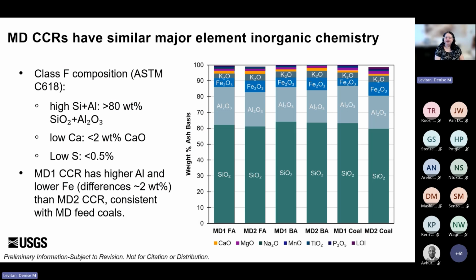So the CCR material from these two plants have pretty similar major element inorganic chemistry, which you can see in the plot here. These are the major oxides shown on an ash basis, which means that they're normalized to not including the organic carbon content. So we found they have these similar ash yields, as I showed in the previous slide, which are pretty high. And then we also found they really are similar in major element composition, really high aluminum and silicon, greater than 80 weight % silica plus alumina. They're also low in calcium, less than 2 weight % calcium oxide. And so if we were going to try to use them as supplementary cementitious materials, they'd be classified as class F as opposed to class C, which means that they have that composition.